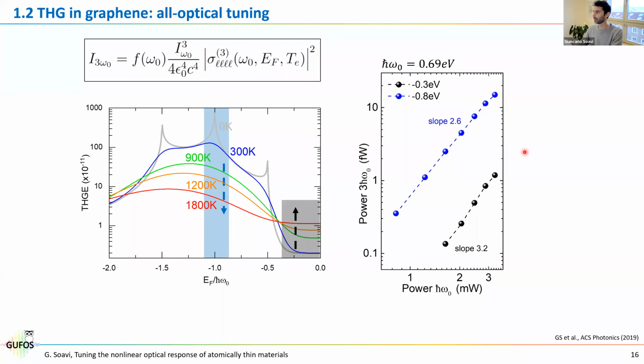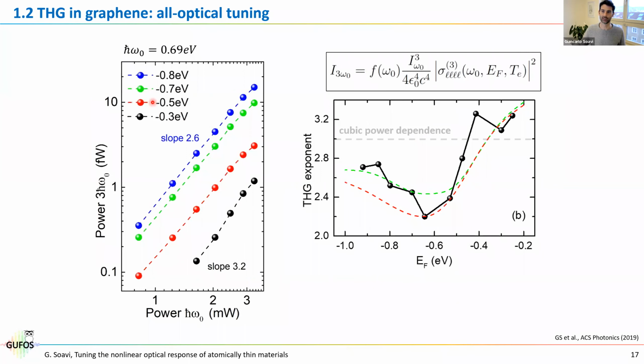And now, of course, we can do the same experiment for different values of the Fermi energy, and this is what we did. And what I plot here now on this graph on the right is the exponent of these power-dependent measurements on log-log scale, so the dependence of the third harmonic over the fundamental for different values of the Fermi energy. And you see that when we are at small values of the Fermi energy in this region, we are above 3. So the dotted line here is the slope of 3. And when we are at large values, we are below 3. And we also have this very peculiar non-monotonic behavior that somehow reproduces the presence of these multi-photon transitions.